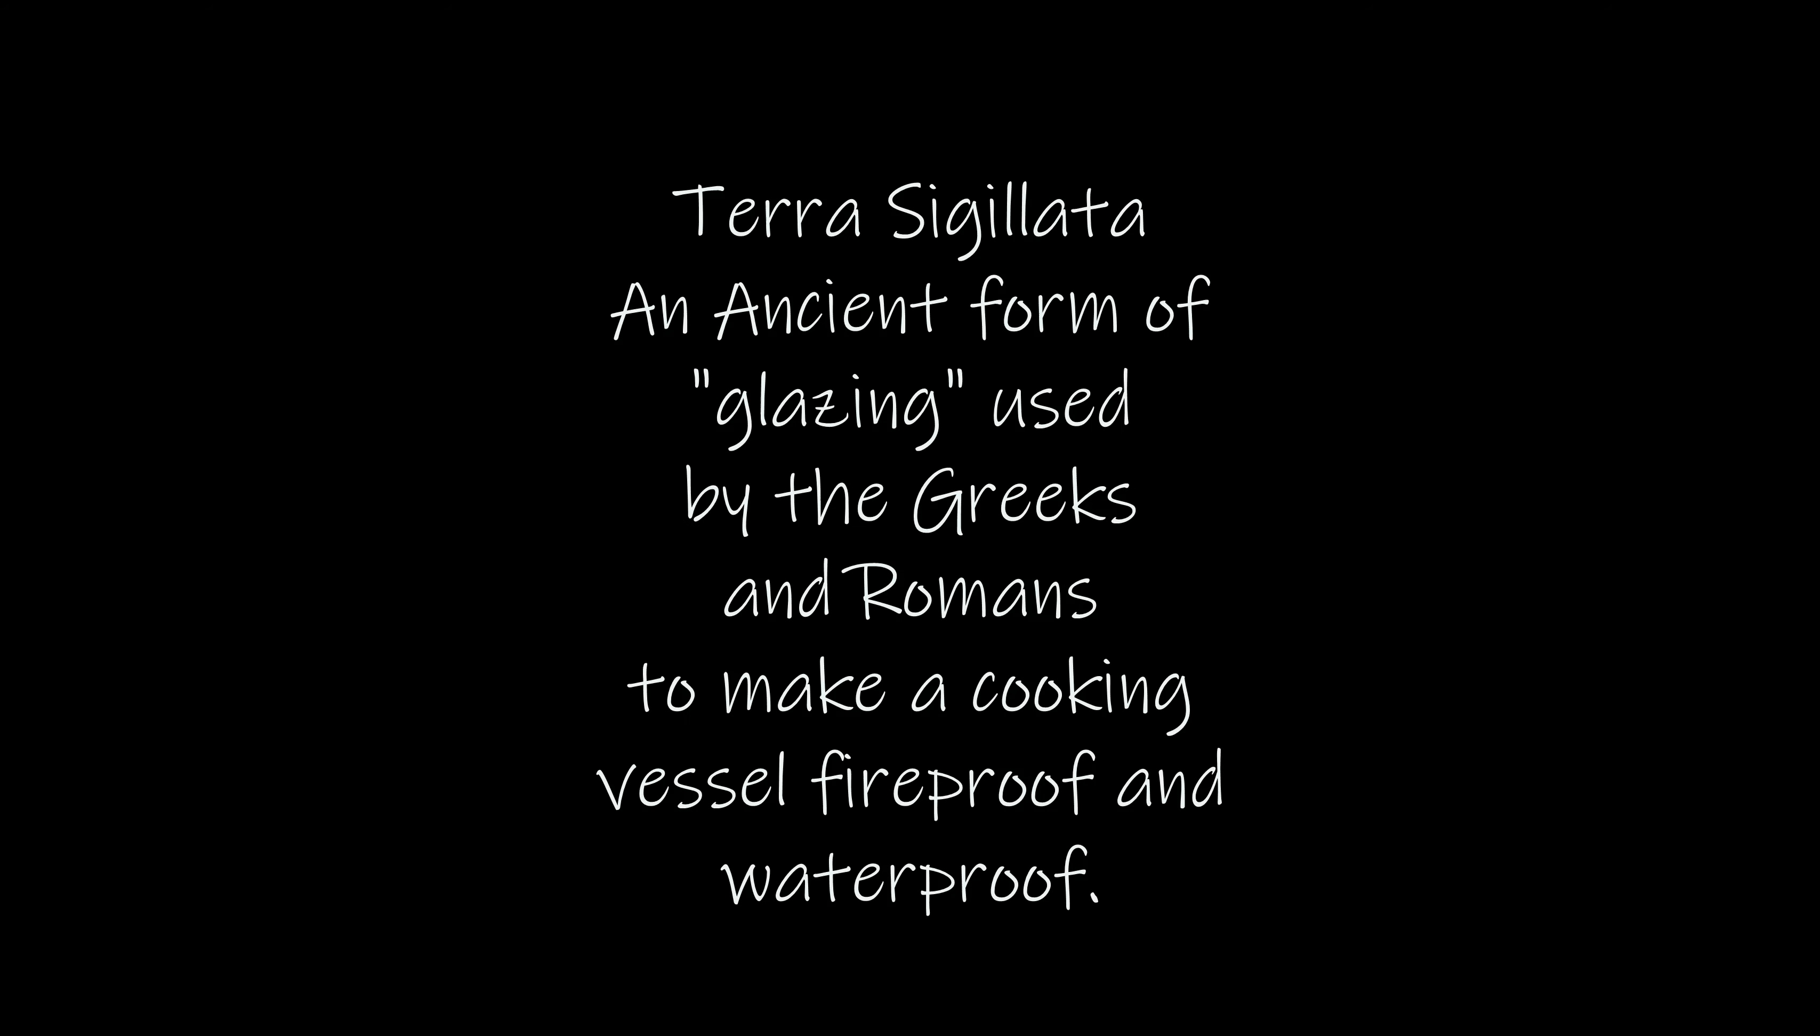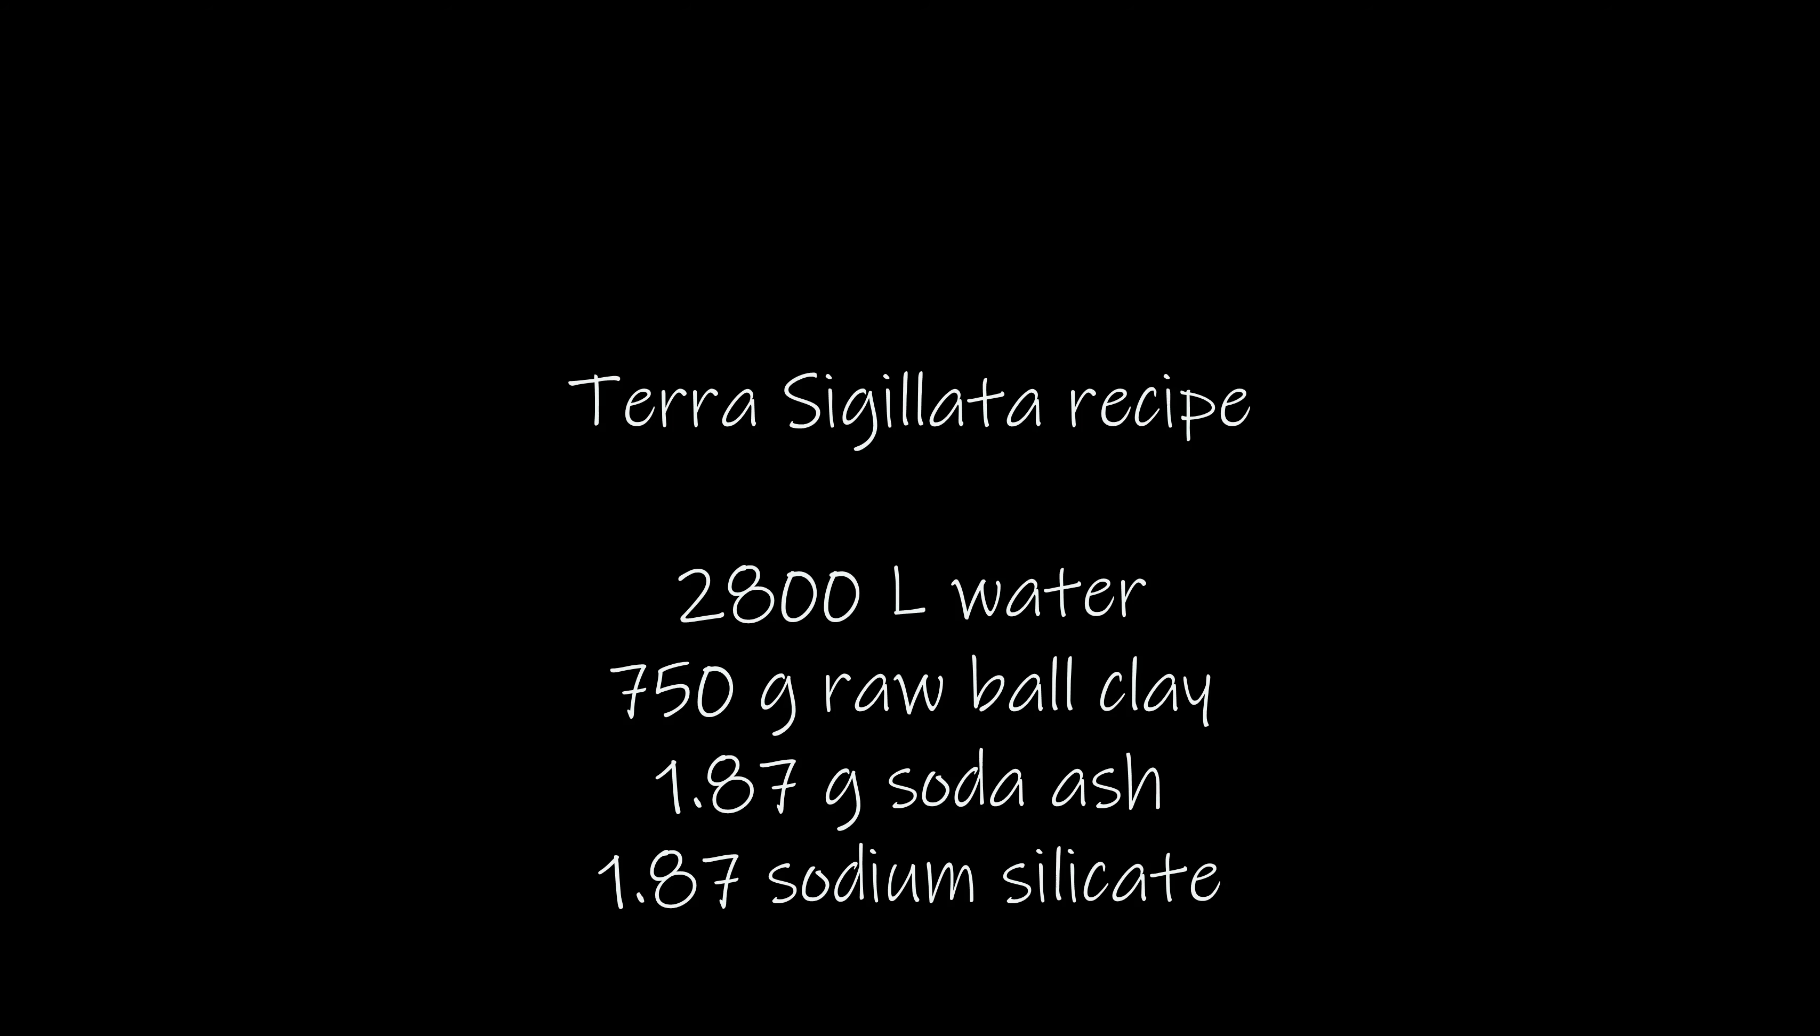The design for this pot was created using terra sigillata, which is a very watery mix of clay. You allow the clay to settle in a bottle. That's a technique which you should google. And then I added some colored oxides to the water to make the colors. I just painted a band around the outside for decoration mainly because oxides are a little toxic so I didn't want to put them in a design over the whole pot.